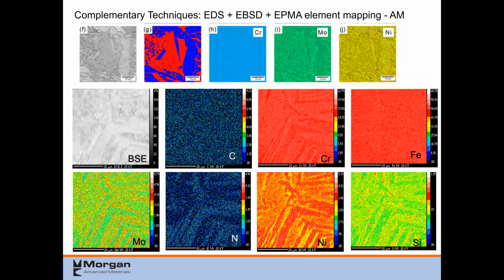This is the next one where, again, you can see very strong grains and composition. And if you look at the nitrogen, you can even bring out the nitrogen a little bit with WDS that you couldn't do with EDS at all. And then when he looked at this, he could see that there were silicon particles scattered throughout the sample, and that was quite interesting because they didn't know that. And then once you do the further annealing and do the HIP process, the silicon actually just goes away, and so you don't see those particles spread around like you do. And so this was a very nice addition to his thesis.